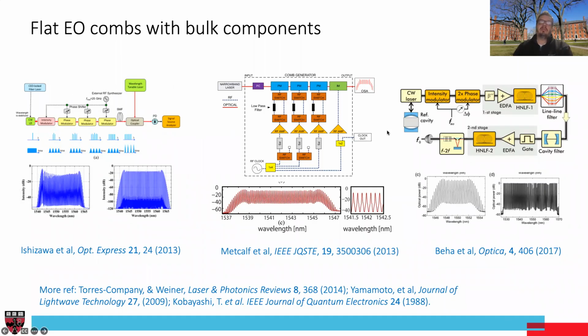Here are 3 examples of solutions that all rely on cascading several modulators, daisy chaining them. For example, in this work by Scott Diddams and Scott Papp, they take an intensity modulator and follow it up with two phase modulators, and by controlling the RF and the phase difference, you can actually get a flat spectrum. In this case, they also followed up this frequency comb, essentially a pulse source, with highly nonlinear fiber and some pulse shaper that allows you to broaden the comb and make it more dense and very, very flat.